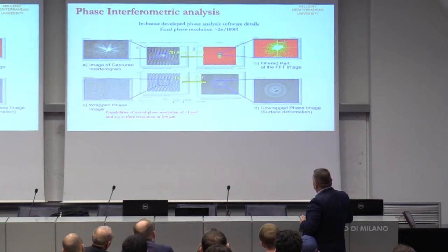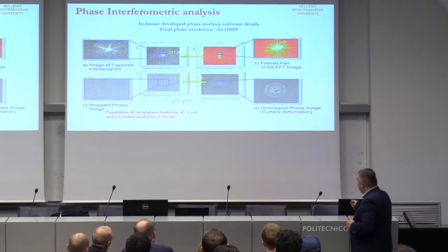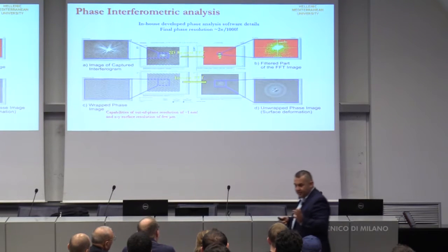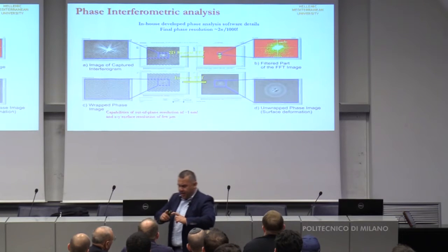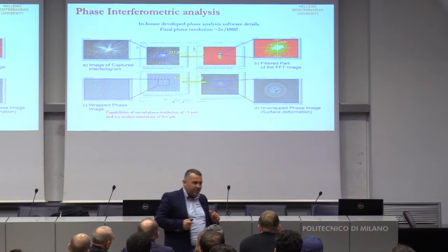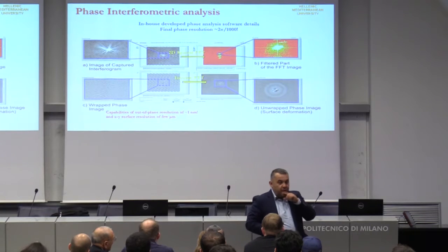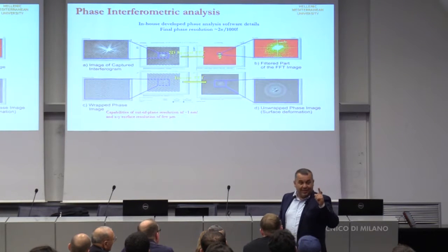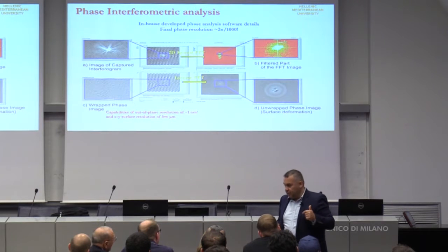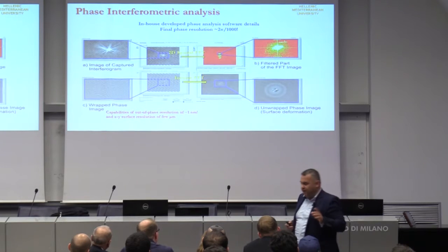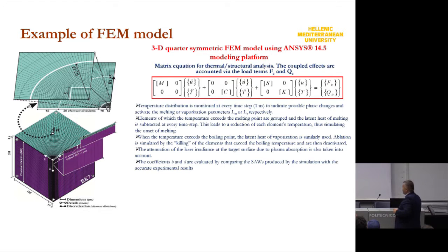We can focus only on the positive component, where we can do a phase unwrapping, for example here, and then we can do an inverse Fourier transform, and finally we can observe the illumination area is here, and here you see a cycle which is nothing else than the Rayleigh wave propagating outside of the surface of the interaction region. And the sensitivity of this method was in the order of 1/1000 of the wavelength of the laser used. So it's something about 0.5 nanometers of this phase method.